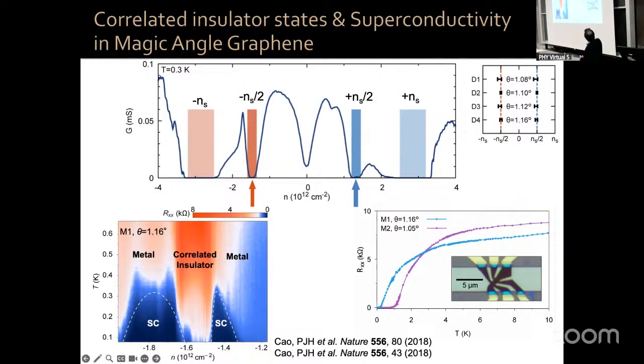By the way, I should mention that this behavior, the correlated insulator and the superconductivity, only happens in a relatively narrow twist angle range around 1.1 degrees, roughly between 1 and 1.2 degrees, which tells you this is related to establishing that flat band condition.